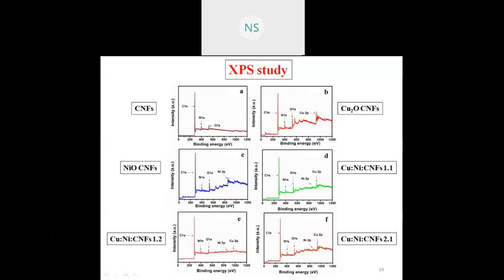So these are the XPS studies for this nanofiber of different ratios, and the same electronic configuration can be obtained for that particular nanofiber. Only a difference in the electronic configuration can be obtained in the case of copper oxide and nickel oxide carbon nanofiber. And when we go with the combination, the combination of these electronic oxidation states can be obtained in the 1:1, 2:1, and 1:2 of this particular material.